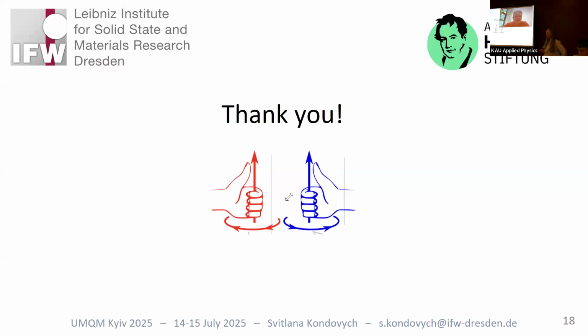Hello, Volodymyr. Thank you for your question. So in our system, chiral symmetry breaking originates from the Dzyaloshinskii-Moriya interaction. For the work of Hertel, which I showed in the introduction, indeed, this chiral symmetry breaking originates from magnetostatic interaction. However, the geometry of the system and the profile of the domain wall, so they have head-to-head or tail-to-tail domain walls, and there the radial component inside the domain wall interacts differently with the magnetic field.